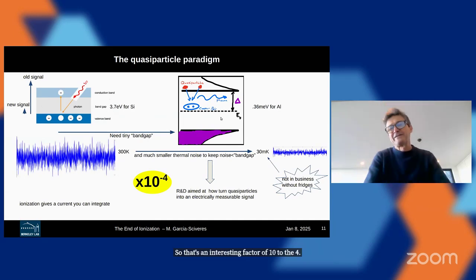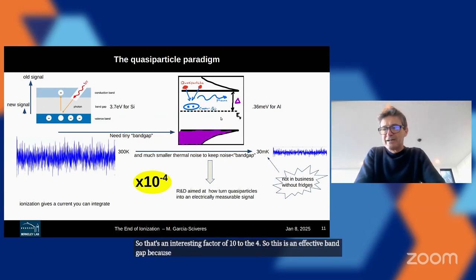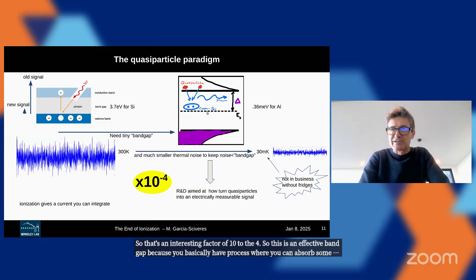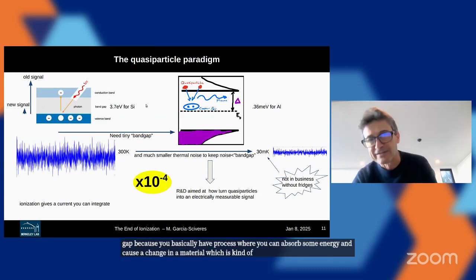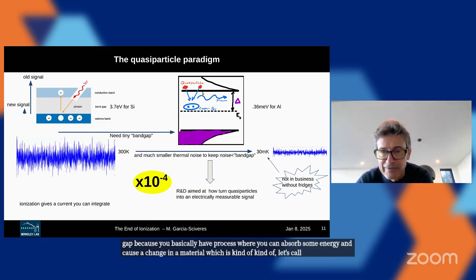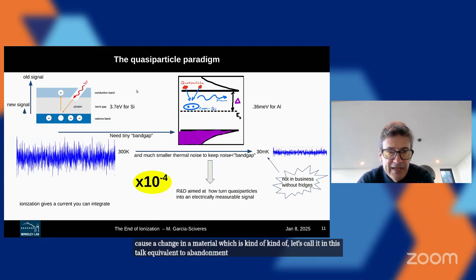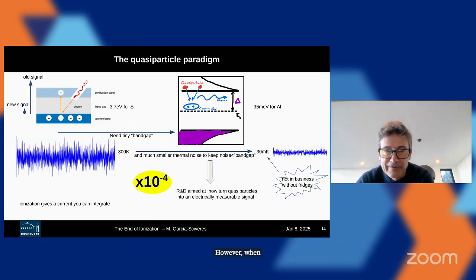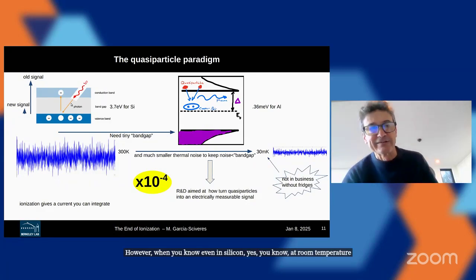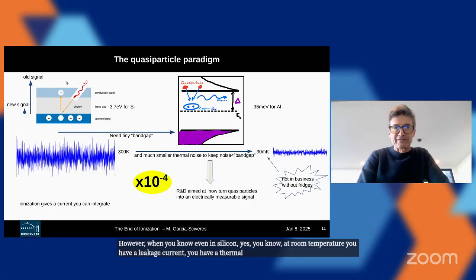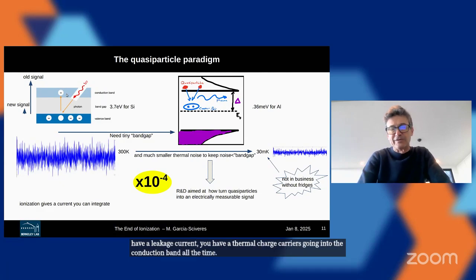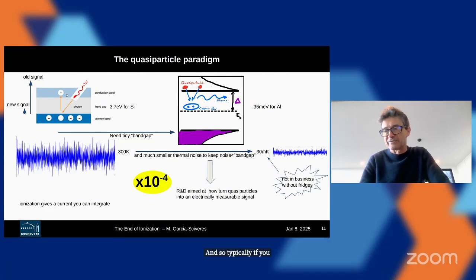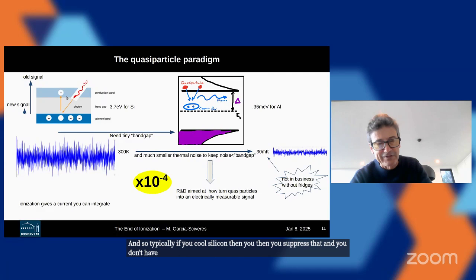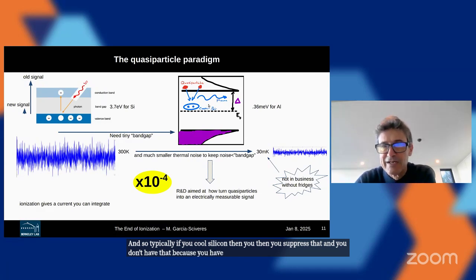So this is an effective band gap, because you basically have a process where you can absorb some energy and cause a change in a material, which is, let's call it in this talk, equivalent to a band gap. However, even in silicon at room temperature, you have a leakage current, you have thermal charge carriers going into the conduction band all the time. And so typically, if you cool silicon, then you suppress that because you have a lower thermal energy. We have to do the same here.